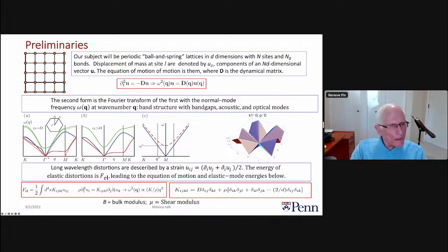What I'm showing here, the dashed lines correspond to a pure Kagome lattice, and there is a line of zero modes that run down from gamma to the point M in the Brillouin zone. Here is a plot of the full phonon spectrum as a function of QX and QY, and you can see you have these straight lines of zeros that come to the base in a V-shaped structure. And there's a zero mode that goes all along each of the gamma to M.